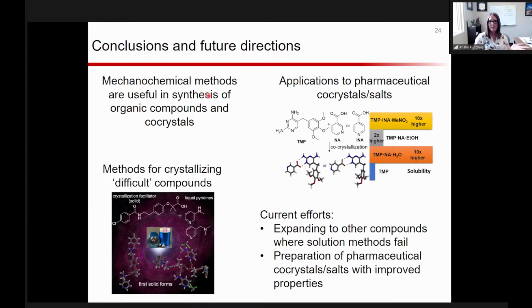We've done a little bit of synthesis as well, of just making new molecules, not a ton of that, definitely more in the co-crystal path. And we're looking at applying these to pharmaceutical co-crystals and salts with improved properties. We're developing methods in targeting compounds that are notoriously difficult to crystallize and trying to use mechanochemistry to control that. And then we are currently expanding to compounds where solution methods are failing and targeting improvements in properties.